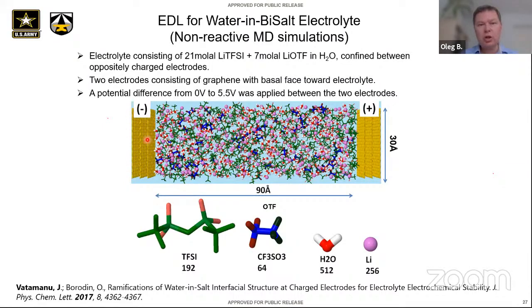In order to do that, Janelle used a constant potential methodology, which he coded in custom code, which allows the electrode to be polarized and respond to the electric field and species coming in from the electrolyte. And the electrolyte, by the way, is treated by my polarizable force field, which has a reasonably good description of the majority of properties in bulk. So we're going to take that, put potentials between electrodes, and see what happens next to the electrodes.